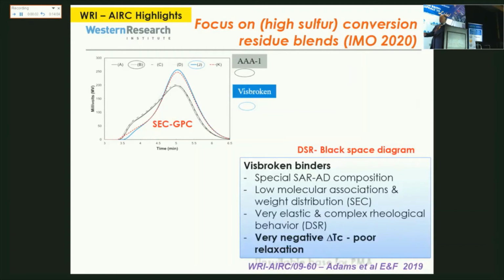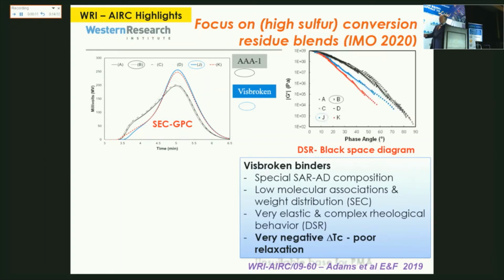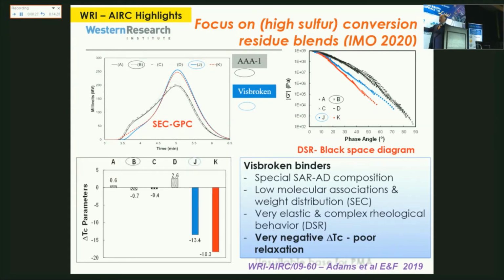And they also show very special behavior in the GPC, for example. They don't have the same type of asphaltenes that will agglomerate. And then if we look at the black space, they also have a very special behavior which is very elastic and brittle and does not relax very well. And if we look at the delta TC, they are very bad in terms of delta TCs. And what is even more interesting is that if you take that one and you polymer modify it, you go to very low delta TC. So please don't use those kind of bases to make polymer modification. You're going to be losing your money for the polymer.